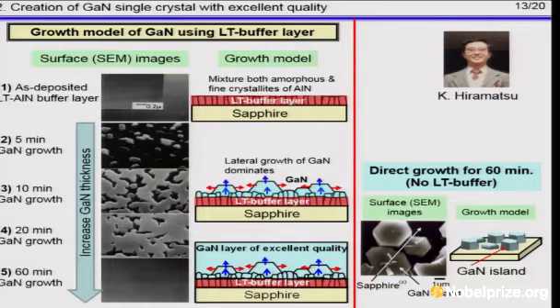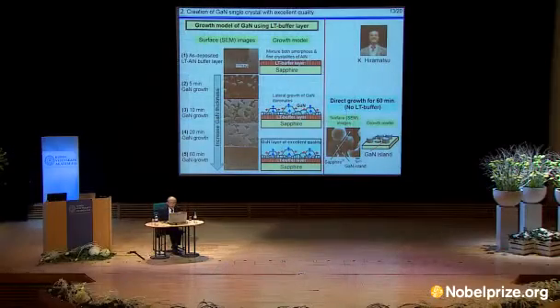On the other hand, right-hand side, in the case of direct growth, gallium nitride with hexagonal column with different height and size grew, remaining bare sapphire surface even for 60 minutes growth.